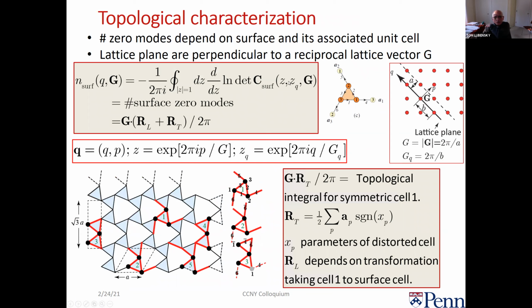So in exactly the same way that you calculate index numbers in the electrical case, we can calculate the number of zero modes at each wave number for a surface whose normal is a reciprocal lattice vector of the system. So you do an integral around z of the log of the determinant of the surface compatibility matrix. Those are things which I can construct by looking at the surface. z is e to the 2 pi i p over g, and z_q is e to the 2 pi i q over g_q. So p is the direction into the surface, into the solid, and q is the direction parallel to the surface.